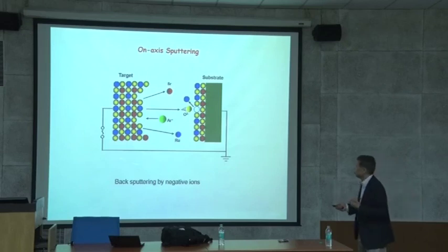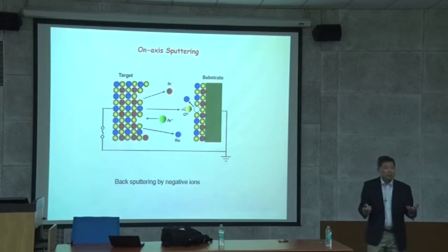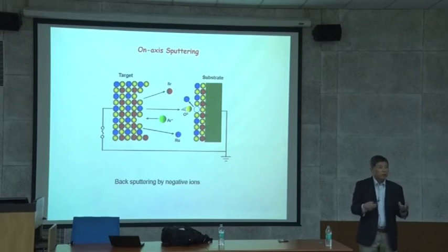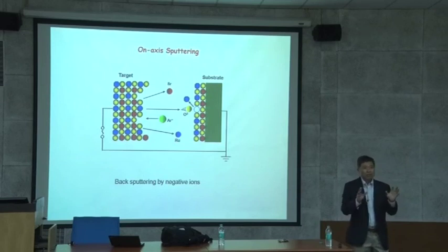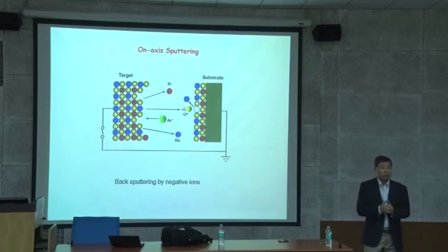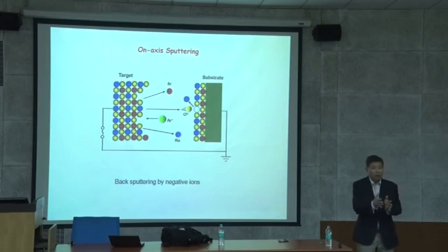So when you do sputtering, most people sputter metals, and a lot of people sputter in a pressure range of roughly 3 millitorr to 10 millitorr. You know that one atmosphere is 760 torr, and this is roughly 3 to 10 millitorr for magnetron sputtering, because magnetron sputtering is much more effective and has higher flux. That's why they developed magnetron sputtering. Okay? That range is the most effective way and gives a high growth rate and so on. In those regions, the mean free path is short, but not very short.